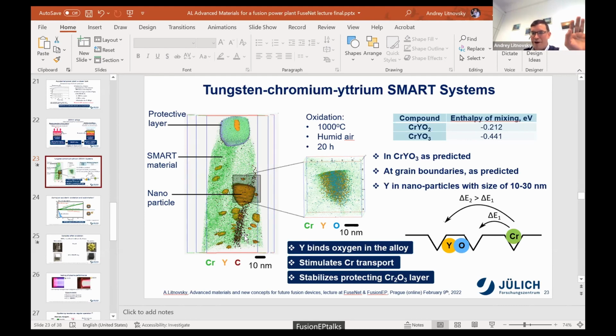If we would have another hour of our investigation, I could show you the protective layer, and this is what we're now investigating with the Oxford colleagues and Warsaw colleagues, how this yttrium at all does this in the protective layer, because here you see nanoparticles. In the protective layer, it is pure chromium, which is framed by yttrium. It is really like holding, like gluing this chromium in between. And this is only something like 5 to 10 nanometers thick. And there is nowhere, anywhere yttrium at all, but it is a continuous layer. What it does, what is the function, we don't know. It is terribly stable and it is really very dense.